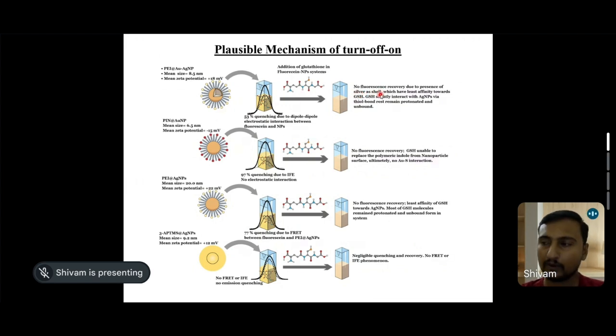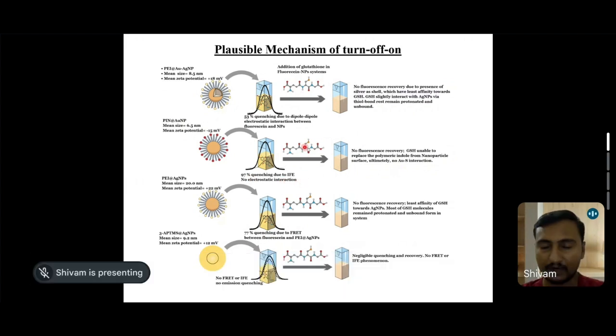Before this, I would like to provide the information that glutathione carries a thiol group that has a very strong capability to interact with the gold atom as compared to silver. So due to the presence of silver on the shell, the glutathione does not interact with the nanoparticle, so there was no fluorescence recovery. Similarly with polyindole stabilized gold nanoparticles, quenching was very good, but after